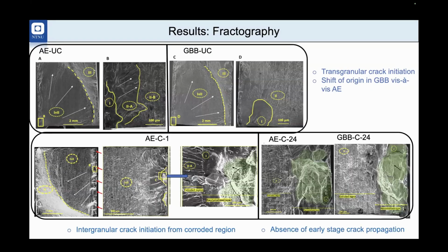If you see the fractography results, you can corroborate what I just said in the previous slide. If you compare the controlled condition with the glass bead blasted, the main difference is that in the control, the fatigue crack initiates from the corner of the specimen at one of the recrystallized zones. But when you compare this with the glass bead blasted, the initiation zone moves slightly towards the interior. This is because of the significant amount of compressive residual stress developed by the glass bead blasting, and as a result the crack initiation zone moves slightly interior, and this is also the reason why you get a tremendous improvement in fatigue life.